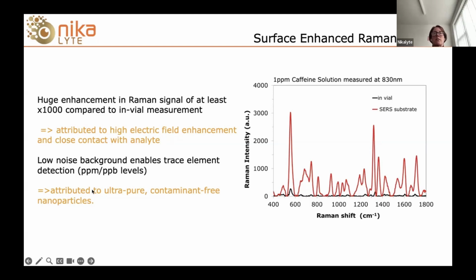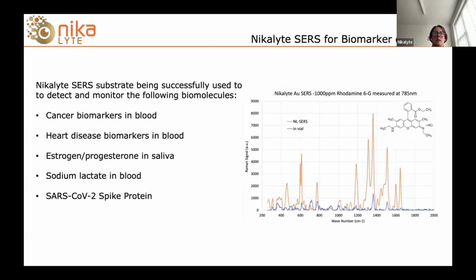And the reason we feel that we have a very low background on our Raman substrates is because of those ultra-pure contaminant-free nanoparticles. We have no other chemicals on the surface. It's just gold. It's gold on glass, and that is it. And that's all you see in your Raman spectra. So when you add your analytes, those Raman peaks that you're seeing are just from your analyte and not from any other contamination. And that's really, really important when it comes to performance.